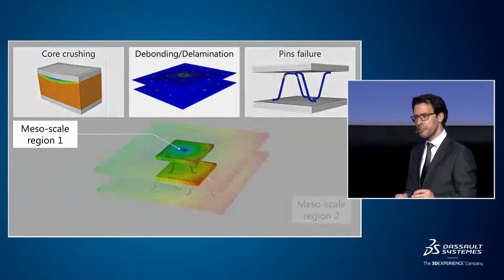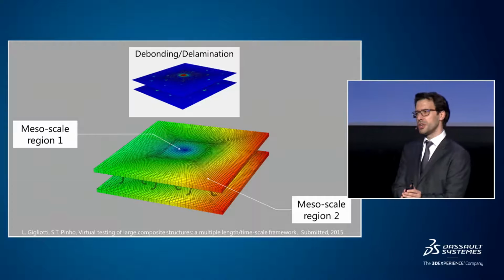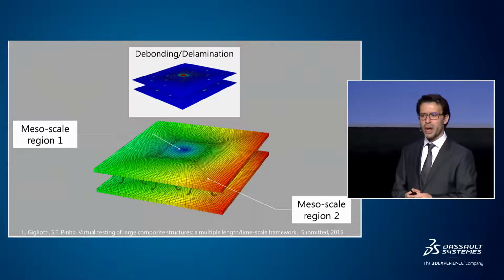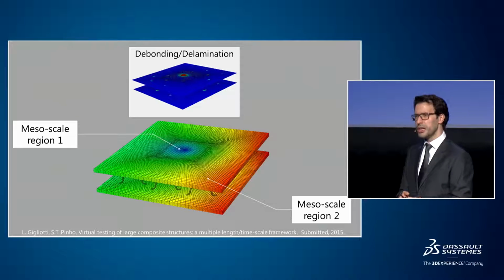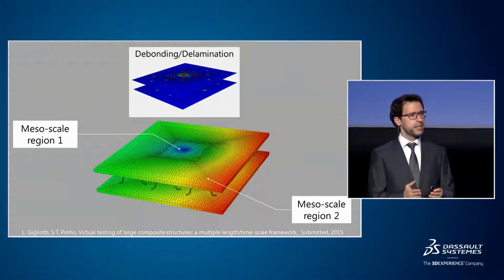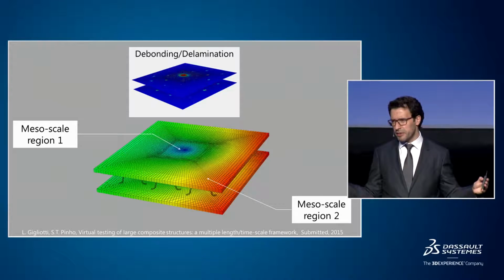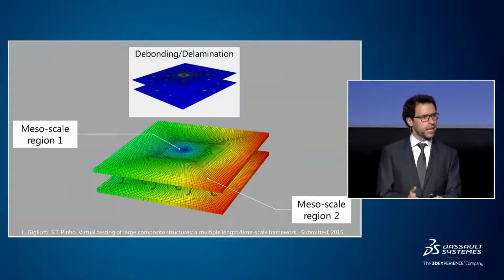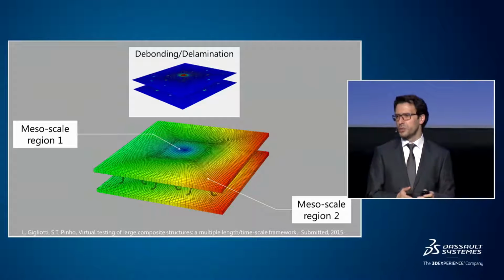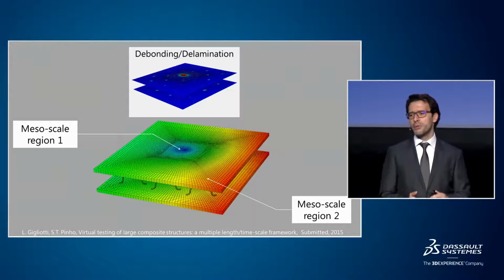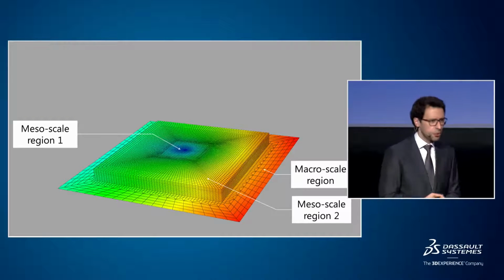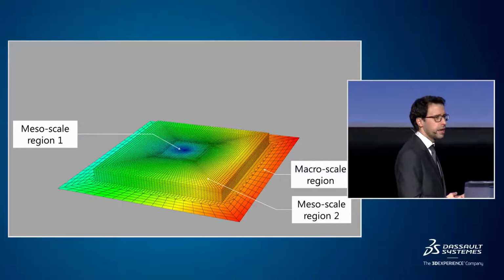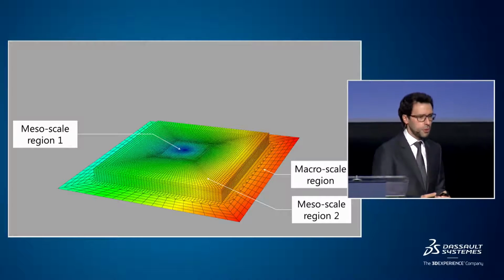Then we have a mesh superposition transition to a second region where now we have only modeled the debonding and delamination. The reason for that is that this type of failure, the bonding and delamination, extends on a length scale which is bigger than that where you have crushing of the core and where you have failure of the pins. And then we have another transition, now between a solid mesh and a shell mesh, again done with superposition.